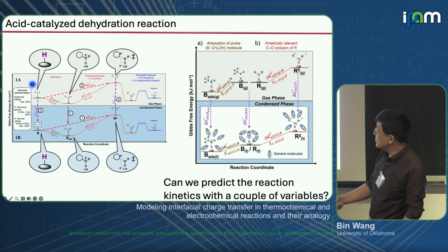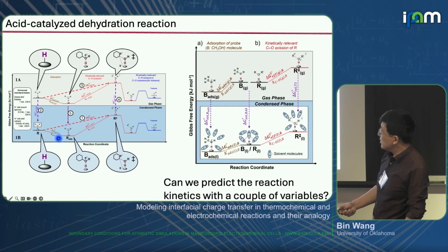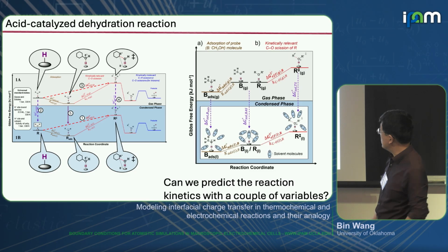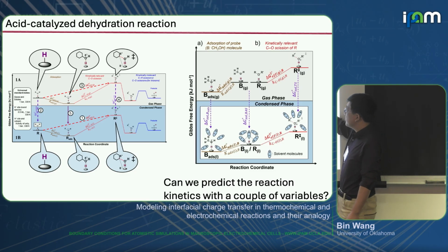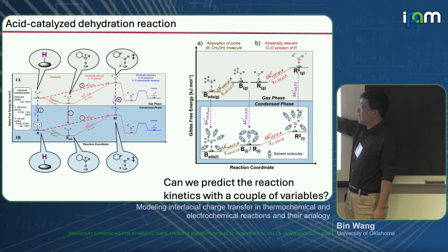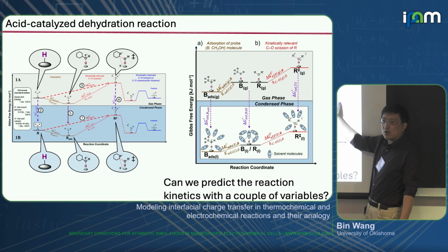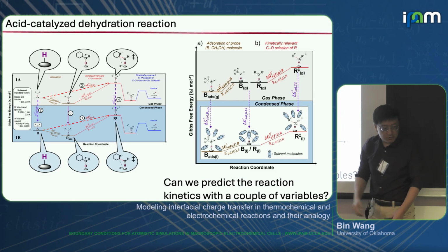Now you put the whole reaction step, but immerse it into a solvent, which is the bottom panel. Now, as I mentioned at the very beginning, your surface species and your transition states probably will experience the solvent differently, and then the activation barrier probably will be different. What I mean is, for example, when you form a positively charged transition state, let's suppose you're doing it in water, and the water has a dipole. The dipole has to reorient to respond to the formation of this dipole at the transition state.